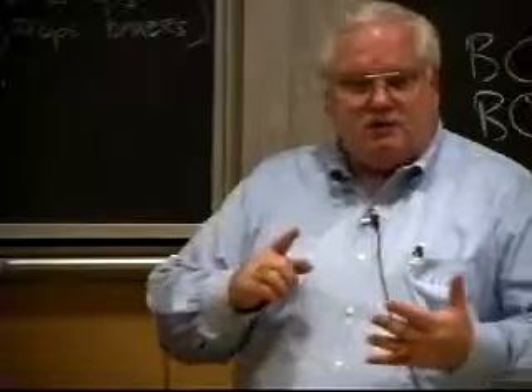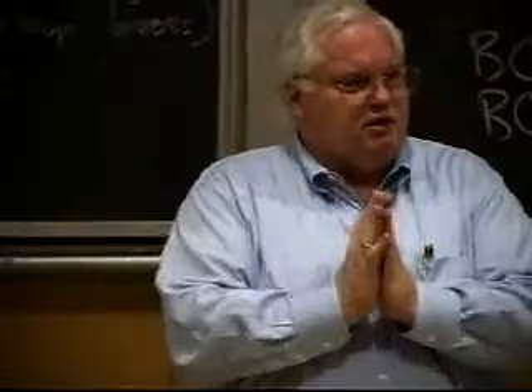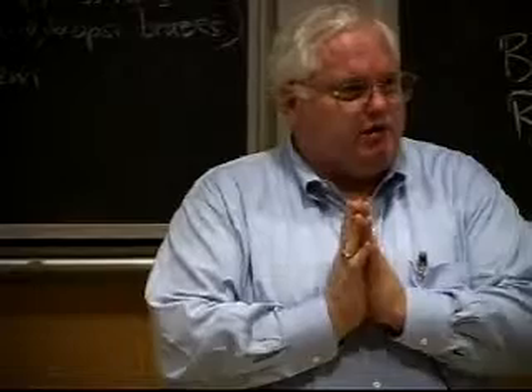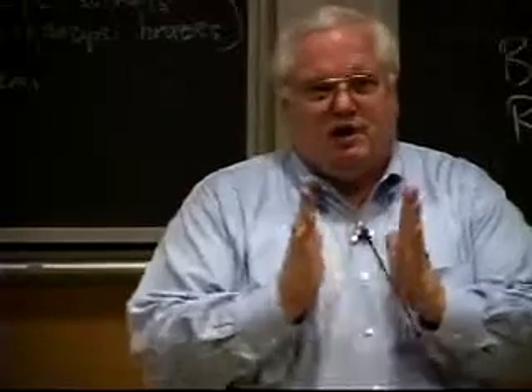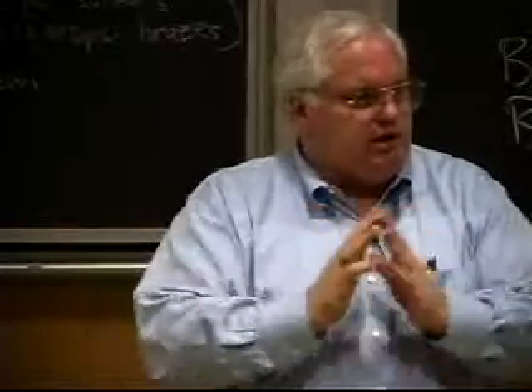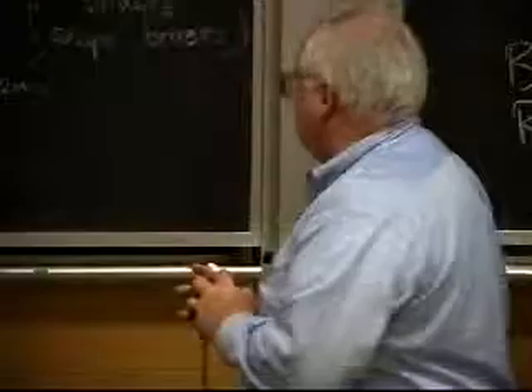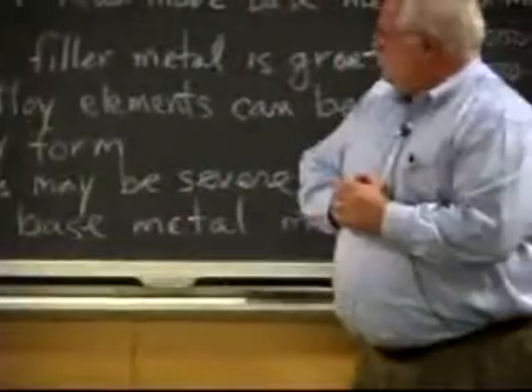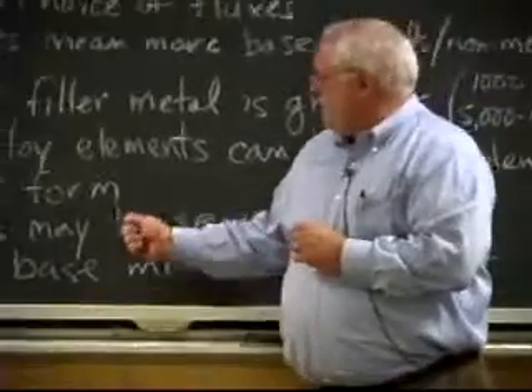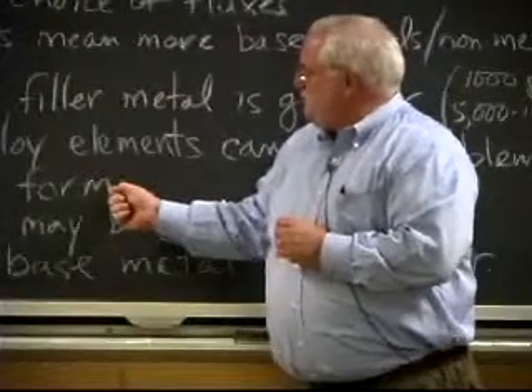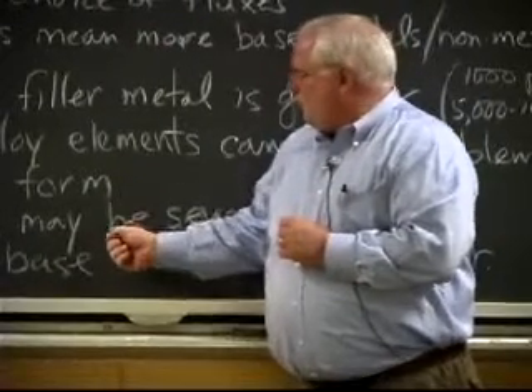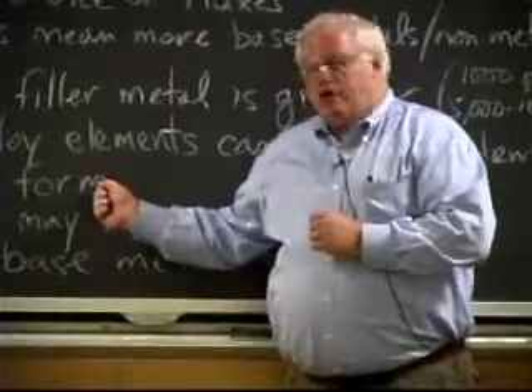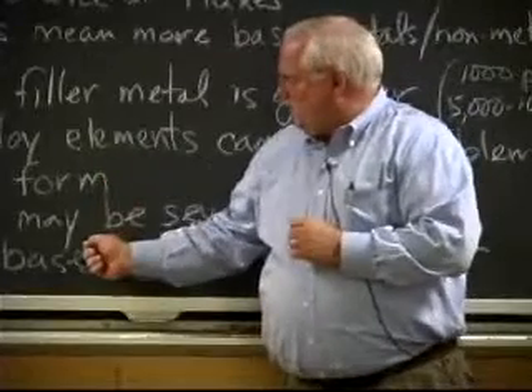we talked about the situation where we had molybdenum and nickel. I talked about the transient liquid phase diffusion bond joint where they were using gold nickel braze alloys, and they got very low ductility in those cross-field amplifiers. That was basically a brazing process. Intermetallics made the joint brittle. And at higher temperatures, we have that occurring a lot more often. It's not to say you don't have intermetallics sometimes in soldering, but you have a lot more in brazing.